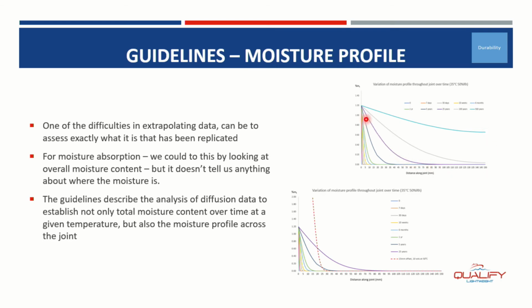In fact, after 25 years, which is an effective ship lifetime, we're only about halfway through the joint, and that's important to give us confidence that the joint's not going to be fully wetted out in the lifetime of this particular configuration. There are other things you can do to accelerate the conditioning. Temperature's the big one, but you can do things like increasing the relative humidity so that you're pushing more moisture in and getting further along in this moisture profile, and also taking part of the overlap length away so that you can then shift that moisture profile.